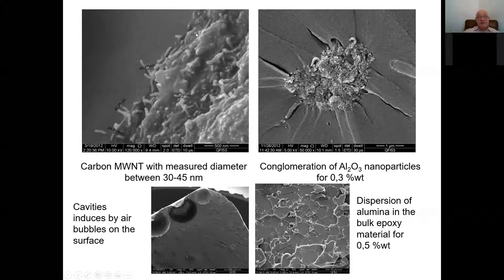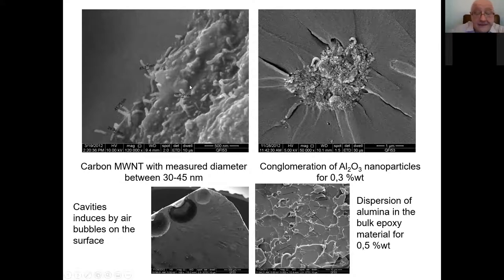From the point of view of multi-wall nanotubes, again, conglomeration is possible, and on the other hand, we have seen from our experience that it is mostly impossible to mix these nanotubes into the resin if you have a weight percentage greater than one. On the other hand, you may have cavities on the surface, air bubbles, if you don't get rid of them. And here, of course, it's 0.5% alumina, again, dispersion which is not really well done. This is not only our problem. I have noticed that conglomeration of nanoparticles and nanotubes is an issue.